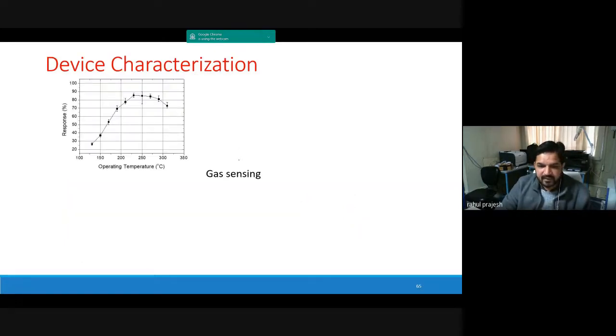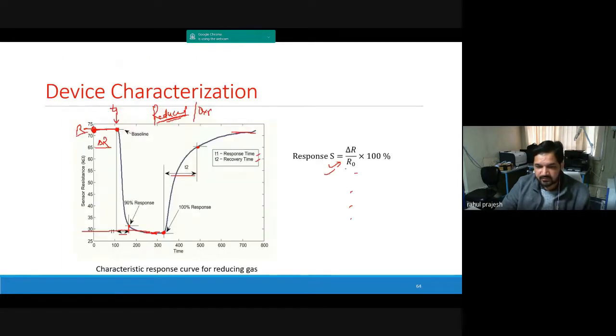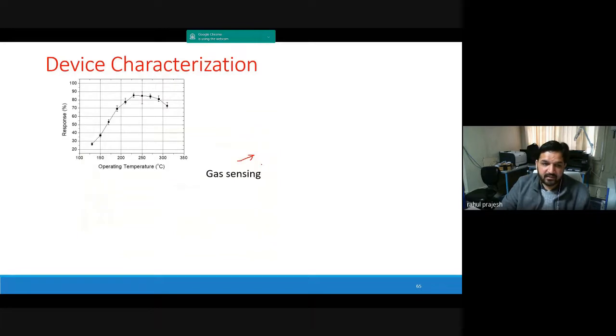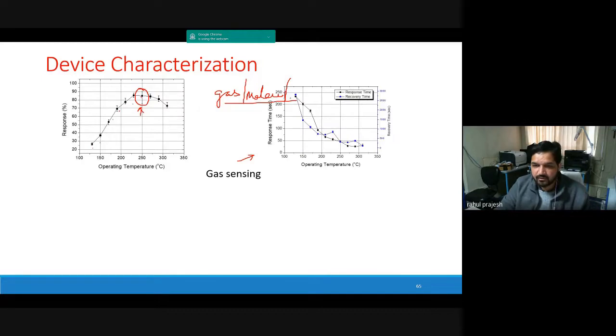At the end of the characterization, you go for gas sensing characterization. So this is the response and recovery time of a typical characteristic curve. But for actual testing, you need to check what is the operating temperature for your device. So you need to test your device at different temperatures, and depending on the gas and material you are taking, this operating temperature will be different. So you need to first find this out. Once you have found the operating temperature, you need to also check the response and recovery times.